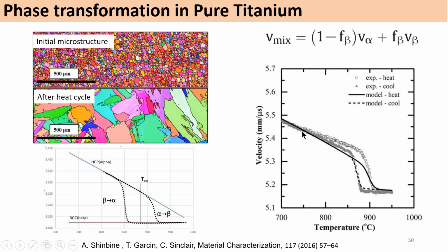So in this pure titanium, HCP is the phase stable at low temperature, and BCC beta is the phase stable at high temperature. And what you can see in this example is that, the same as in steel, we can capture the change in velocity quite well. As we heat the sample and cool down the sample, we can see the hysteresis corresponding to the beta formation and beta decomposition in this metal.